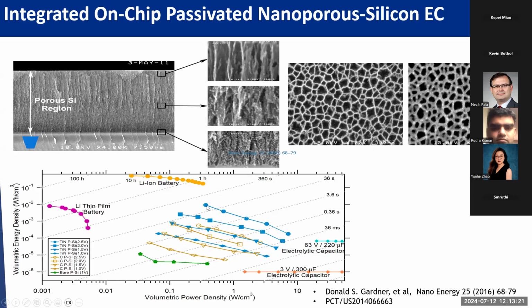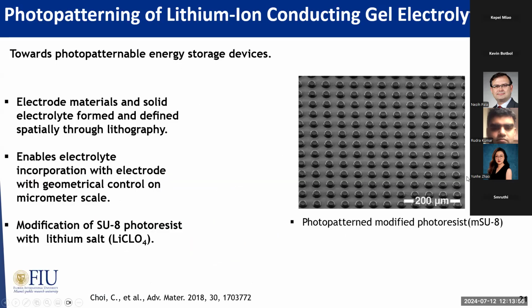So coated materials actually have a much better performance. You can see the titanium nitride on porous silicon, which different conditions we can push it further. So compared to lithium-ion batteries, we have a much higher power density, but the energy density is still low. But it's almost equivalent to the thin film battery in this case. So that's a very promising result because we are pushing to the wafer process.